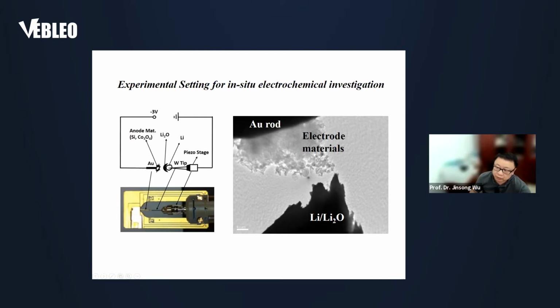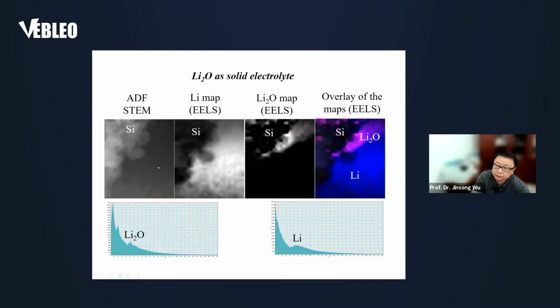And by doing so, we can build a miniature battery inside the TEM column. And then we can apply either a positive or a negative potential so that we can initiate either lithiation or delithiation and observe them inside the TEM with high resolution.